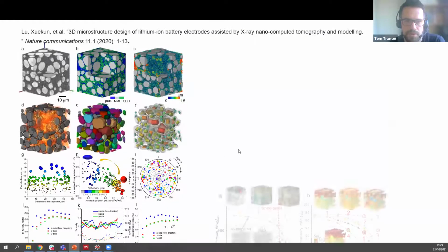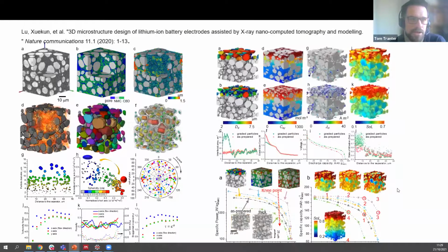And here are a few figures from a paper that came out last year in Nature. What Xuekun actually did was take these baseline images, conduct simulations, and then make adjustments, artificially, if you like, to the images themselves to adjust particle size distributions and microstructural effective parameters such as porosity and tortuosity, and then rerun the simulations and look at the effect on the capacity and specific power of the cell. It's a very interesting paper. I encourage you all to go and look at it.